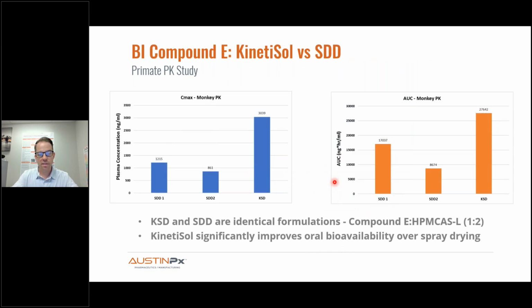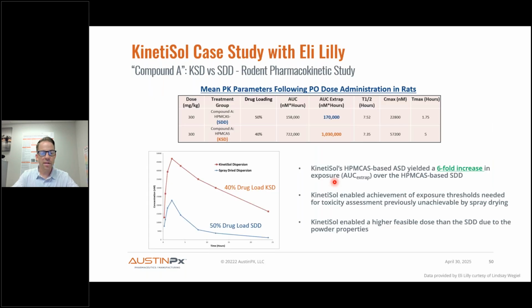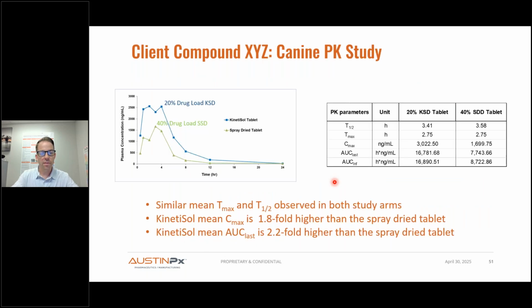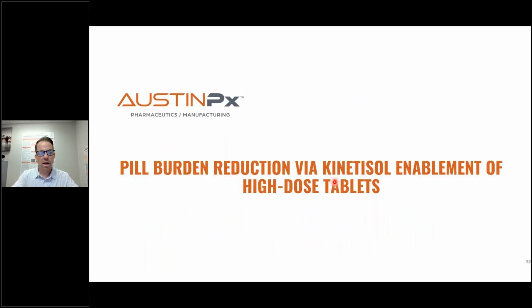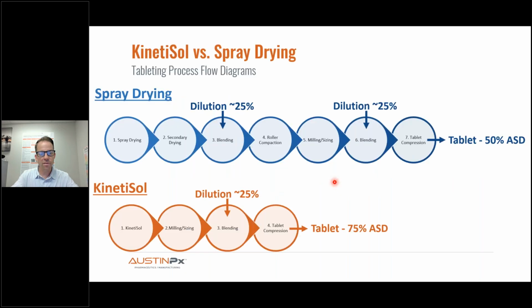Here's a couple of studies. That was compound B, this is compound E. This is a primate PK study, once again, showing kinetisol has a significant improvement in exposure. And then here's a more recent case study with Eli Lilly showing the same thing. Spray dry dispersion versus kinetisol, HPMCAS based, we had a 6-fold increase in exposure. And once again, a recent client study where we reduced the drug load and improved the ASD and converted from SDD to KSD.